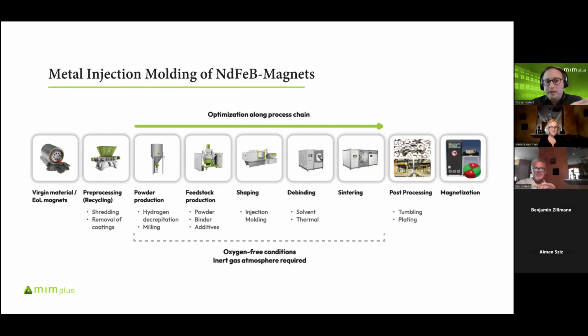So the polymer is only needed to get a flowable feedstock that can be used for the shaping process. I think that's the biggest challenge in communicating this to people. It's not a bonded magnet. We don't have residual binding material. This is a sintered magnet. The fact that we get to near net shape during this process using some kind of plastic bonding material is almost irrelevant to the end product. Exactly.